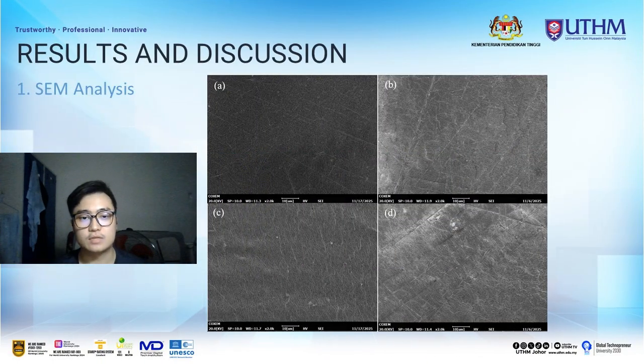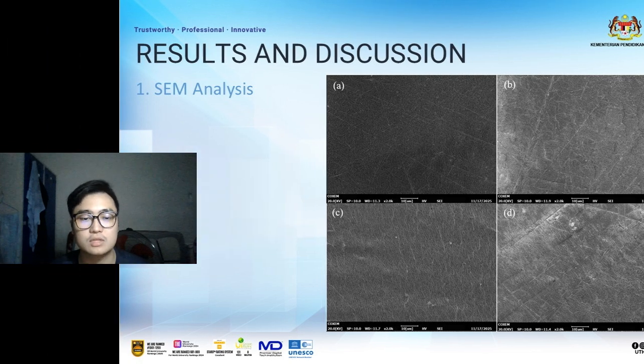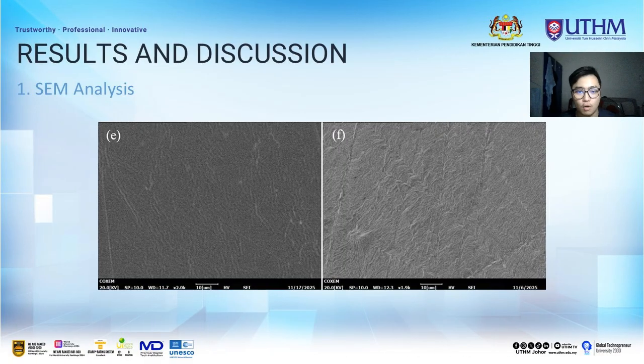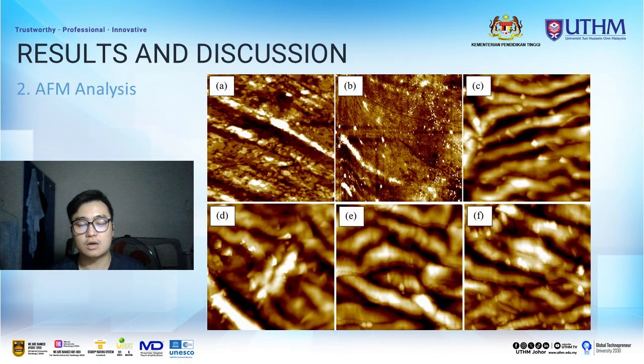As for the results, for my SEM analysis, no grain structure was observed, indicating the Mo thin film was very fine and formed a smooth, continuous layer on the PET substrate. The surface coverage improved as the deposition time increased. As for AFM, the surface roughness, or Ra, increased from 3.33 nanometers at 3 minutes to 30.362 nanometers at 18 minutes. This shows that the film becomes thicker and the surface becomes more textured as Mo accumulates on top of the thin film.